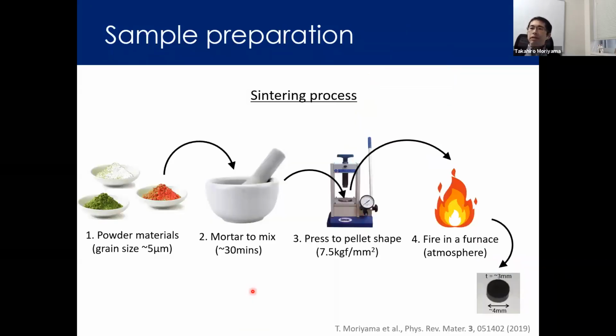I should say that the samples shown in this presentation are all bulk materials made by a conventional sintering process. We basically start from the powder material, mix them together, press to pellet shape, and fire in the furnace for some time. And then we get a pellet of this size. The diameter is 4 millimeters and the thickness is 3 millimeters. Okay.